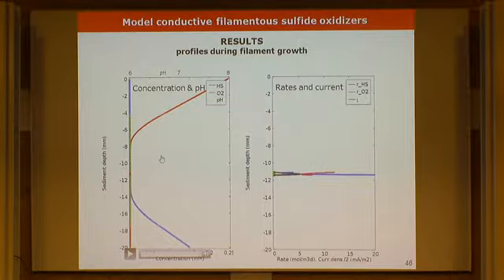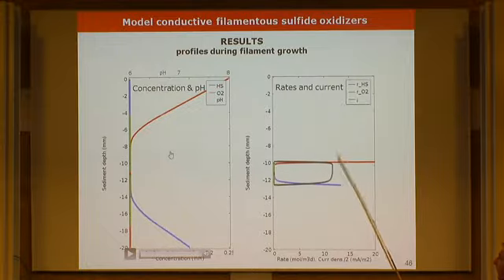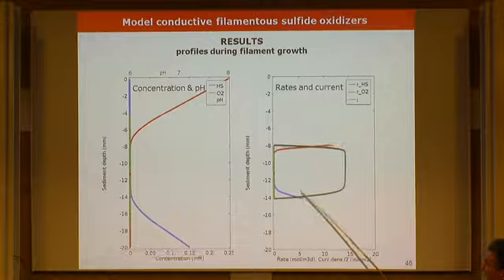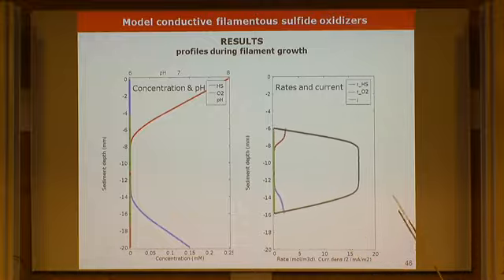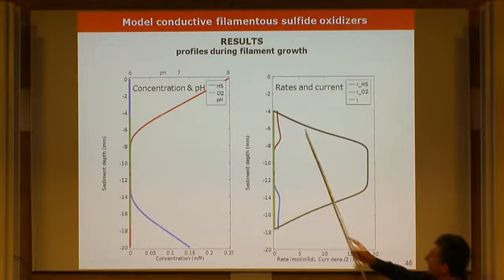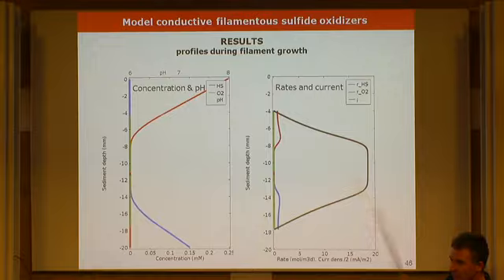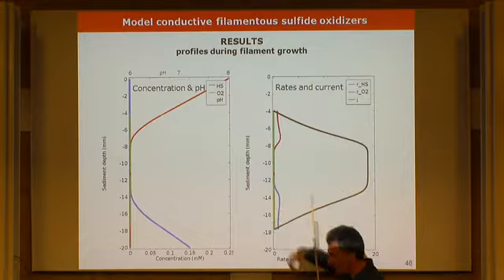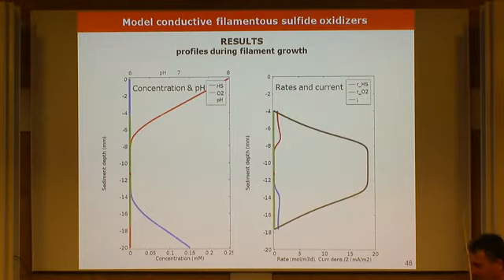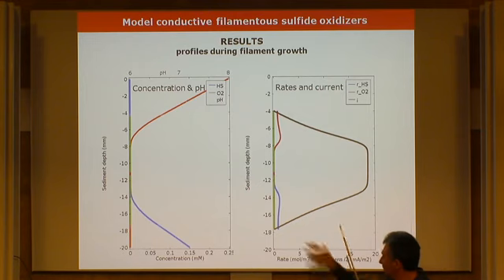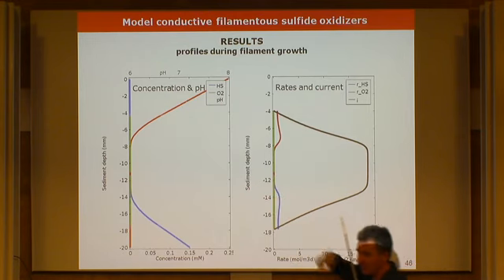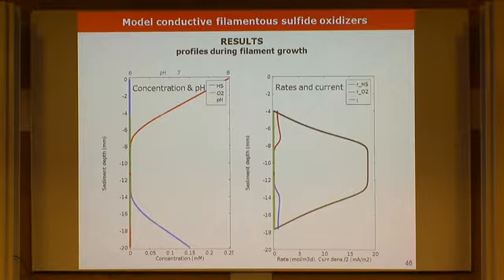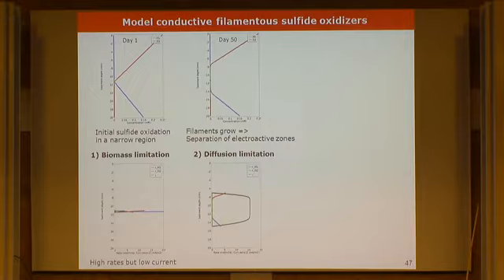So you see this much better if I show you also the other one. This is sulfide oxidation, this is oxygen reduction. As the filament grows, the electrochemical zones become wider. And you can imagine that the longer the filament, the more resistivity it has. So there is kind of an optimum here where they can stay, and then nothing happens. So I think we can conclude that we would have three regimes here.